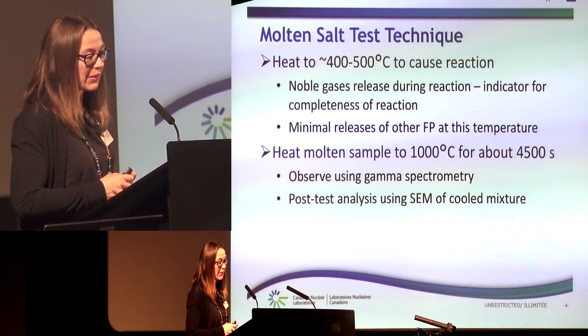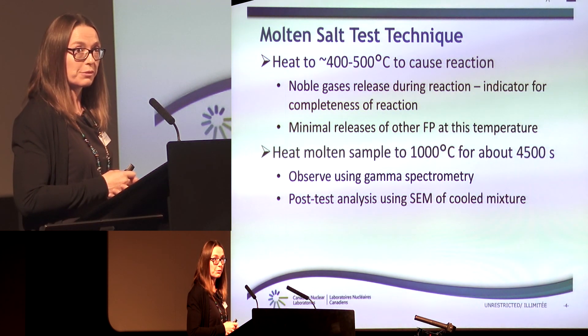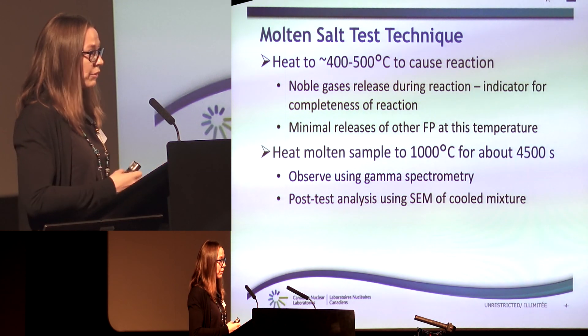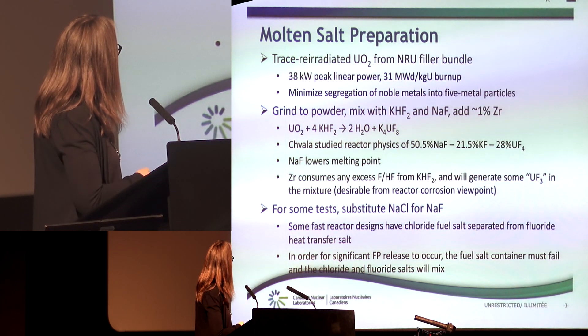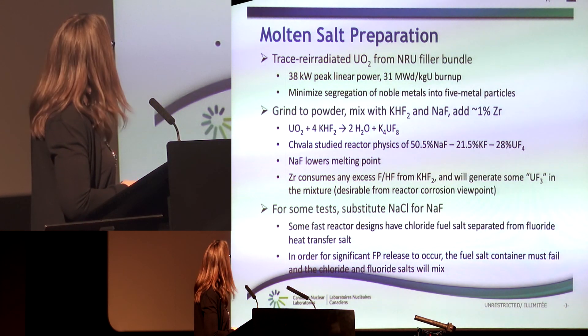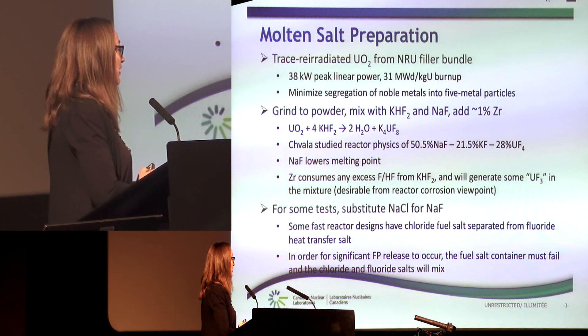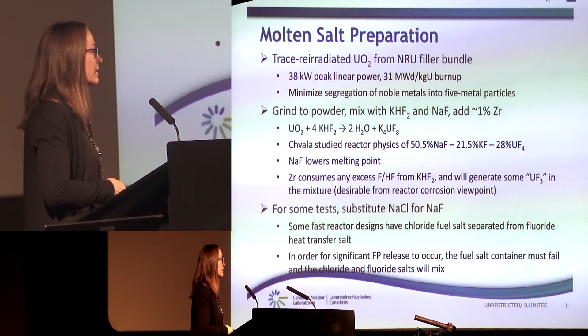That mixture of different fluorides and the irradiated UO2 or thorium dioxide was processed at around 400 to 500°C for conversion between oxide and fluoride. One issue is that this process forms some water, which with fluoride creates hydrofluoric acid. But under severe accident conditions, we can't avoid that — we won't end with an ideal conversion method when talking about severe accident conditions.